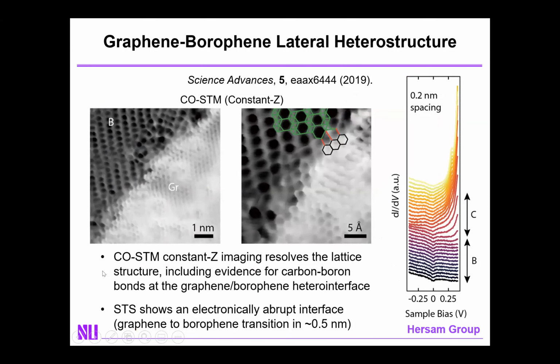You can also look at the lateral heterostructure. We find that CO STM imaging most directly reveals the bonding in these lateral heterostructures, and it's quite interesting to me, at least, in that you can see on the graphene side, you have essentially perfect graphene lattice. On the borophene side, you also see that hollow hexagon structure I showed you before. And now you can inspect the hetero interface. And even though these materials are not lattice matched or even symmetry matched, you find that the distance over which you go from perfect graphene to perfect borophene is literally on the order of 1 nanometer. So over a couple of lattice constants, you transition from one to the other.